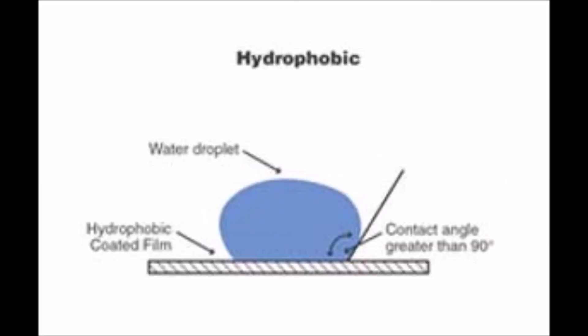The relatively hydrophobic surface of silicone hydrogels, however, produces a poor wettable surface. The nature of it being hydrophobic is due to the silicone hydrogel molecules being nonpolar, causing the intermolecular forces to be weak and thus not attracted to polar molecules like water. Moreover, the contact angle for hydrophobic materials is greater than 90 degrees, as shown in the graph.